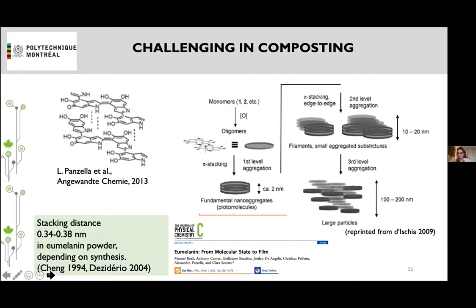I was telling you that we're hoping to have a somewhat higher mineralization rate. And we think that if we didn't observe this rate, it's because of the very complex structure of the material, this hierarchical structure. You can see here, for instance, that we have the building blocks and then they form tetramers. The state of the art in the literature is that we have the tetramers of the building blocks, and then they aggregate by pi stacking, and then the stacked structures interact through hydrogen bonding. But this means that the structure is kind of compact at the nanoscale, and so somehow difficult to be accessed by the enzymes. And so we are actually running studies, especially resolved studies at the nanoscale, to try to promote the de-stacking of the molecules.